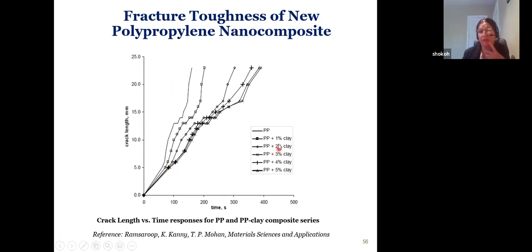If I add 1% nanocomposite clay, I see that improvement. If I start with a very small crack, I need more time to reach that 10, I get more time to reach it. So you get a longer resistance to crack progression.